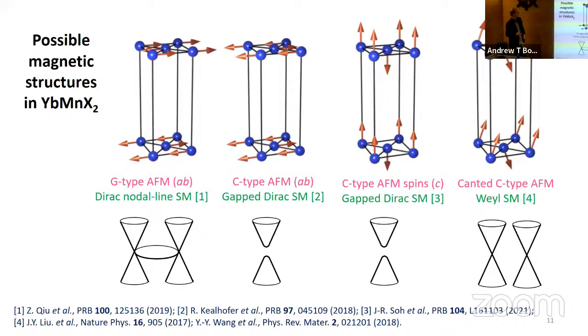And until quite recently, the magnetic order in this material was not known, the structure that the manganese magnetic moments adopt below, actually around about room temperature, and there were a few suggestions. And there were some theoretical predictions based on ab initio calculations. One group, for example, suggested that the magnetic structure looked like this, where each spin is in the opposite direction to its nearest neighbor, both within these layers and also along this direction here.